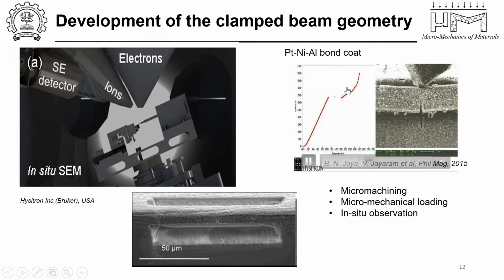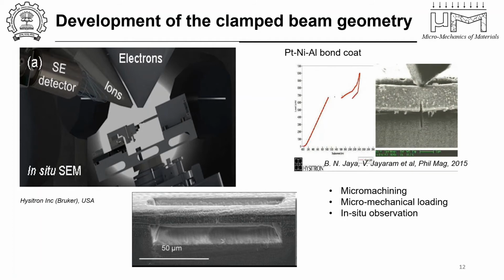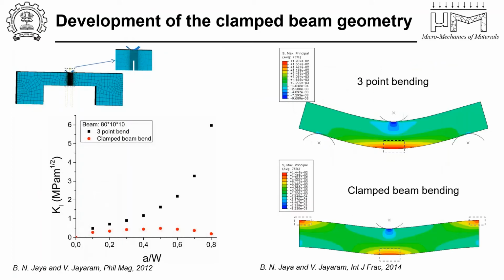Now, is this a material property that it is able to take higher loads, or is this something to do with the geometry itself? This is what we were perplexed about. We assumed that one could use the single edge notch bending configuration to obtain the K1C of the material. So we took a look at that. We modeled the 3-point bending beam and the clamp beam bend configurations, and obtained the stress intensity factor K1, plotted as a function of the different a/W.